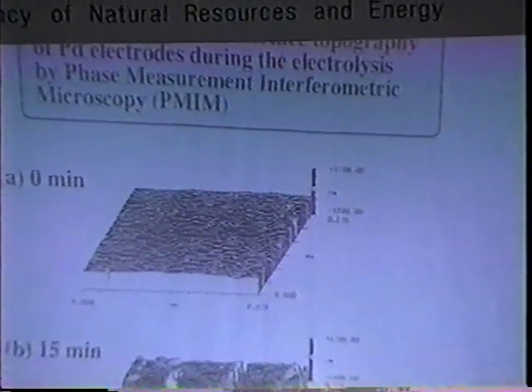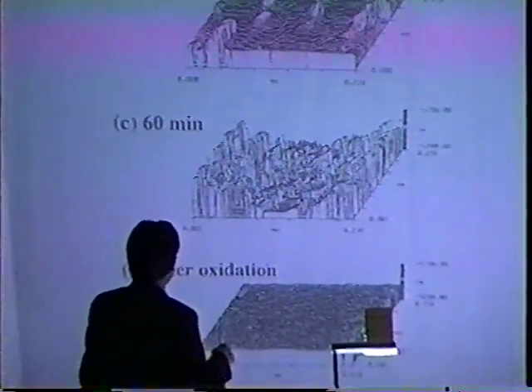Also, we directly observed the surface topography change of the cathode by using phase measurement interferometric microscopy. The palladium cathode surface became rough in the course of electrolysis due to hydrogen absorption, even at very low hydrogen content. But the original surface is fully recovered by using this palladium as anode or just leaving it in air for 24 hours to desorb hydrogen from palladium. We also show some results obtained for palladium single crystals and palladium-silver alloys. Thank you. Okay, thank you very much.